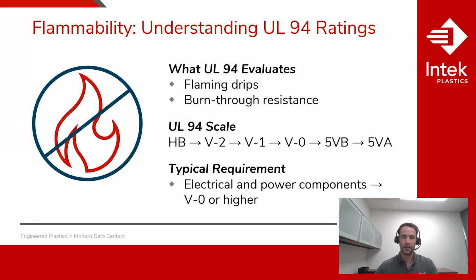And then in terms of increasing performance for a vertically oriented specimen, the lowest rating is V2, which denotes a material that may self-extinguish but would produce flaming drips of molten polymer that ignite the cotton ball. A V1 rating is for a material that self-extinguishes and might drip but doesn't ignite the cotton ball. And a V0 material would self-extinguish without any flaming drips. And this is a common requirement for electrical and power components that you might find in a data center.